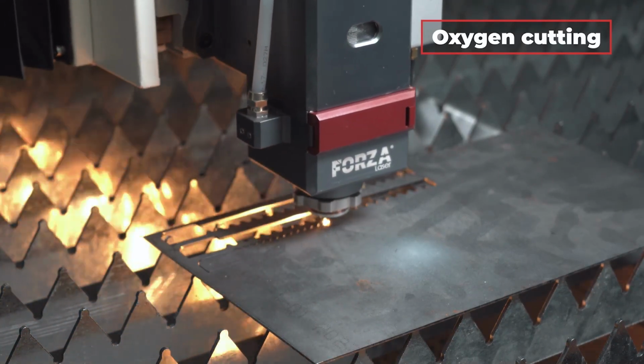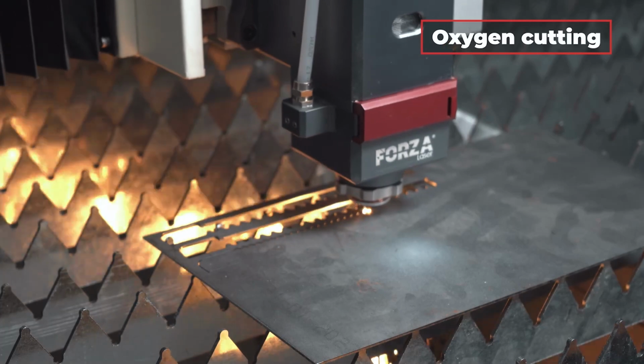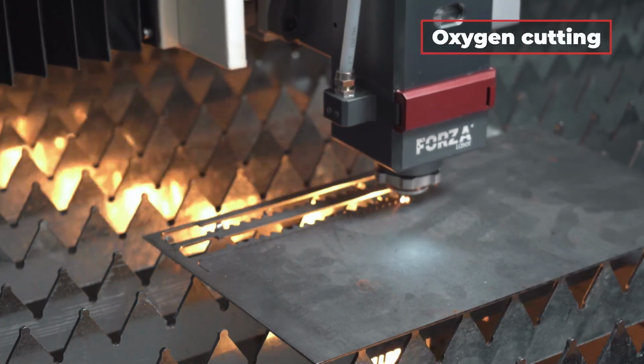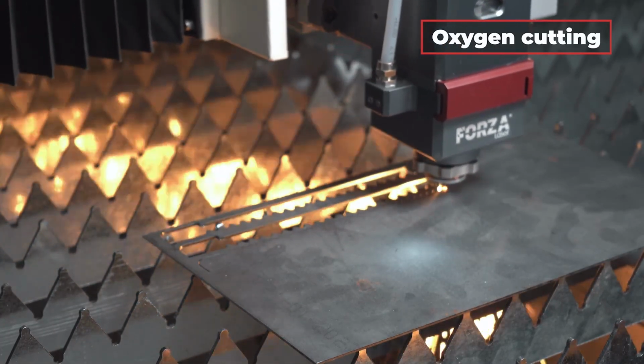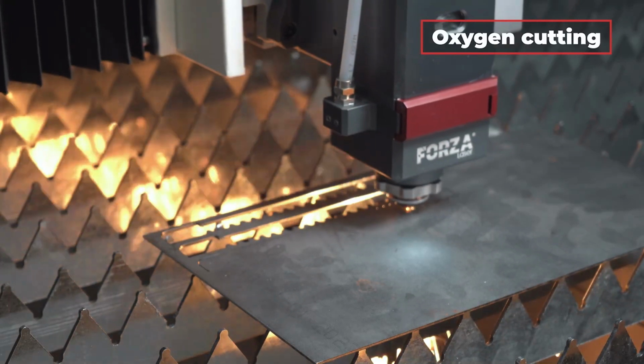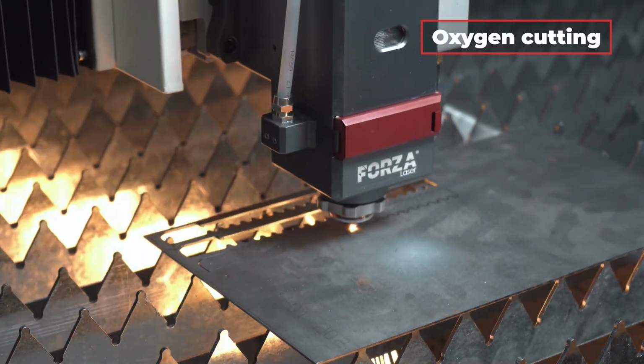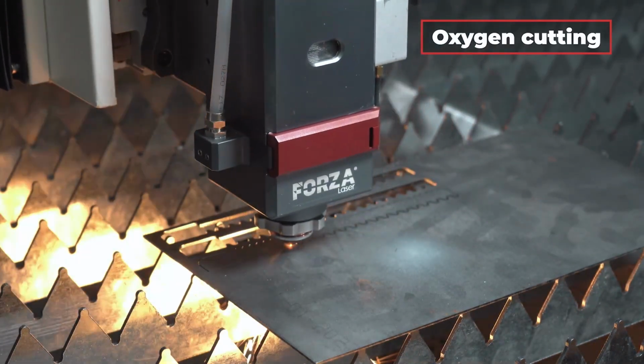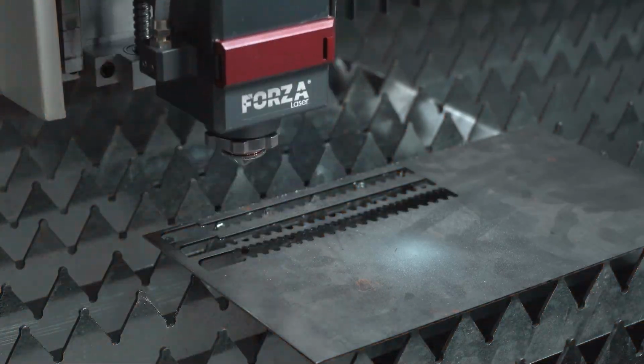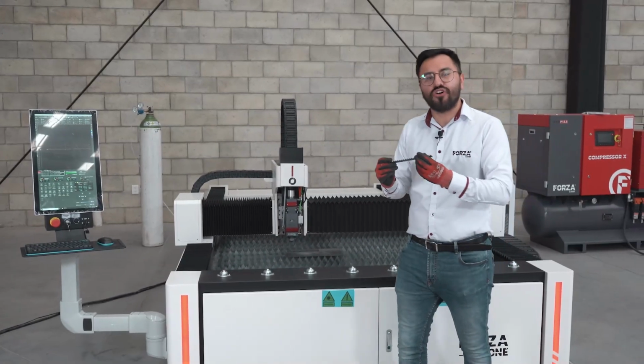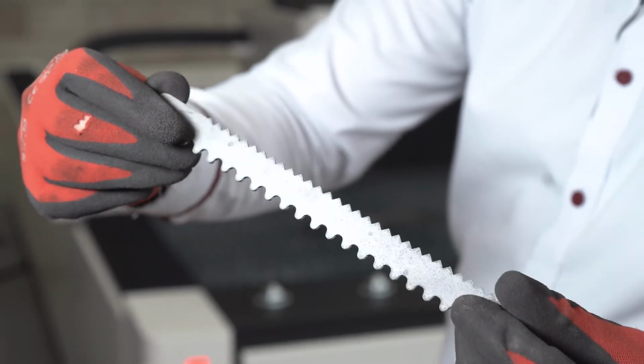As you can see, the cut creates a higher flame due to the increase in combustion. The machine operates more slowly because the combustion must be very controlled. The thickness of the line on the piece is wider because the heat is greater and a larger amount of material melts. This is the result of the hot cut using oxygen with our 1500 watt machine.